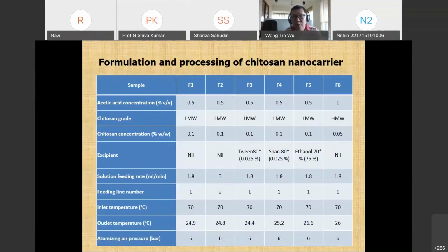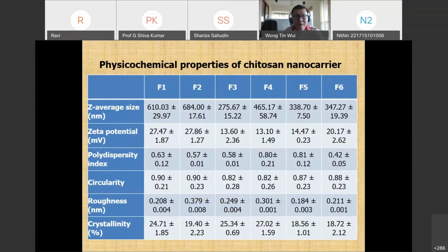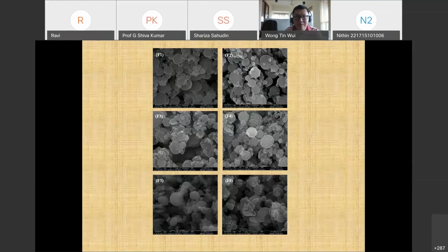With this hypothesis in mind, we prepared 6 variants of solid chitosan nanoparticles by spray drying. We varied the acetic acid concentration, chitosan grade, molecular weight, and chitosan concentration. Also, we used different excipients, Tween, Span, and ethanol, in order to prepare 6 different types of chitosan nanoparticles with different physical-chemical properties. The physical-chemical properties of the nanoparticles that were evaluated are size, zeta potential, polydispersity index, circularity, shape, surface roughness, as well as matrix crystallinity. These properties are evaluated because they are the features that will dictate the nanoparticle inhalation efficiency. You can see that the nanoparticles prepared are rather round in shape.